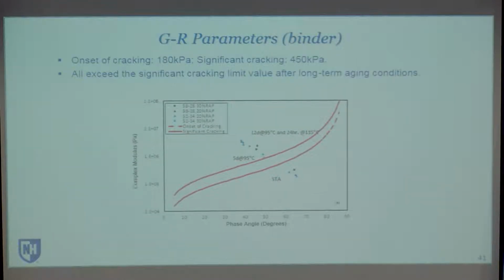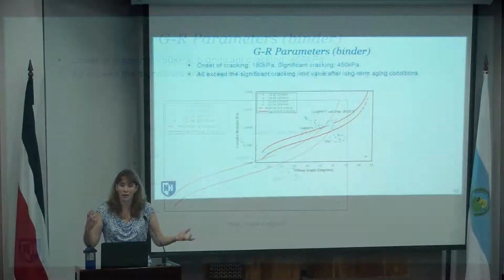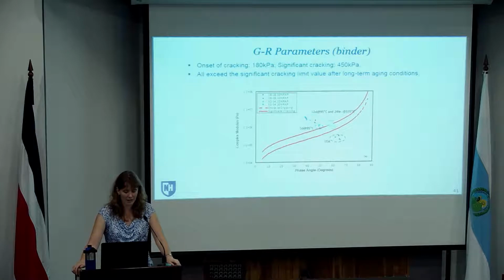We can do the same thing looking at black space, looking at the Glover-Rowe parameter. So again, this is looking at a particular temperature frequency combination, so one point, and plotting it in terms of the complex modulus versus the phase angle, and comparing this to some of the thresholds that have been established, and look at how those materials are changing as a function of aging. So you can see again from the short-term aging, we're in that zone where we're expecting good performance from these materials, and as we age the materials, they're moving through to the point where they're beyond the thresholds that have been established for those significant cracking limits. So again, just something to start thinking about in terms of what's happening with these materials over time.